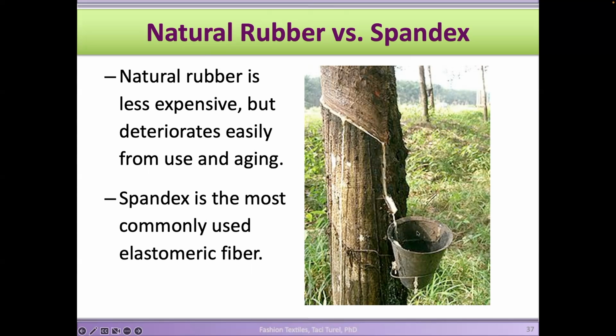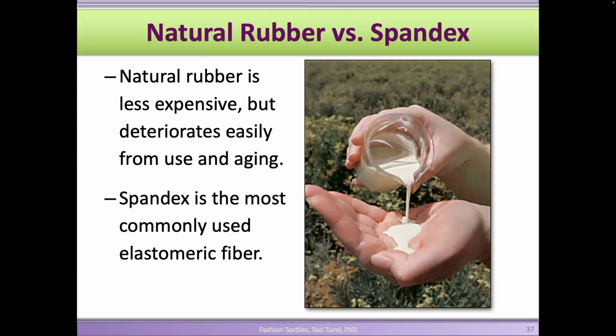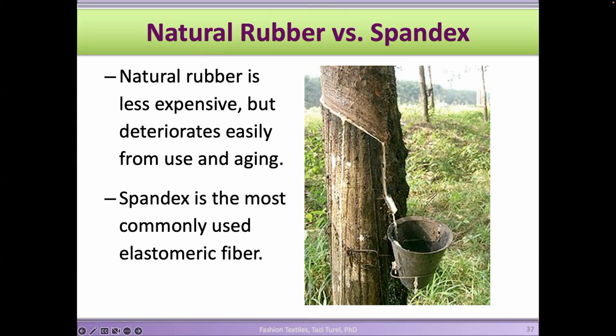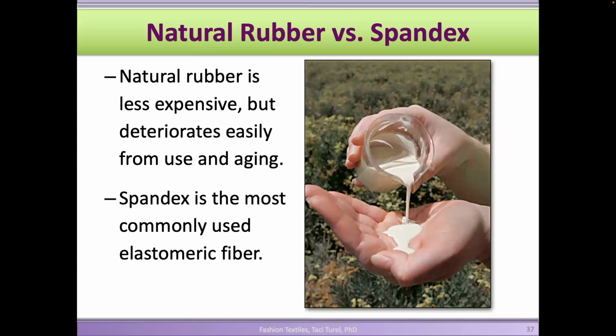vulcanize it. And some say it was an accident. Accidentally, some sulfur got into the rubber, and they realized that it really strengthened rubber so that in hot temperatures, rubber didn't start loosening up or softening. And in cold temperatures, it stopped being so brittle because of the vulcanization. And this was invented by somebody called Goodyear, and he's the one who actually came up with Goodyear tires, because rubber was one of the main materials in tires. And Goodyear was the person who figured out a way to make rubber last longer in different types of temperatures.